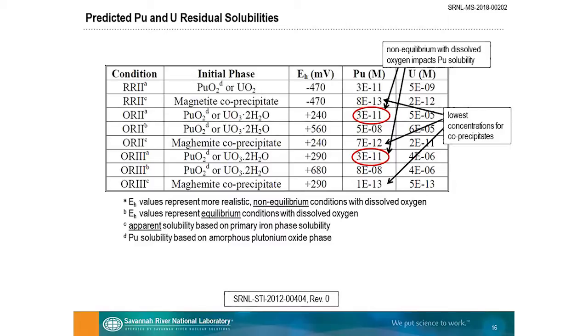And then they looked at cases where rather than having a pure phase, you had a coprecipitate phase. You saw from the compositions, this is mostly iron and aluminum and other species. There's always been a question, how do the metals exist? Are they individual particles, plutonium, uranium, or are they coprecipitated within this other matrix? So they also looked at coprecipitated phases where the solubility of the radionuclide was based on the solubility of the coprecipitate phase, in this case, iron phases, maghemite, magnetite. So those give you the lowest predicted solubilities in the table. But in general, the performance assessments tended to use the higher solubility predictions.